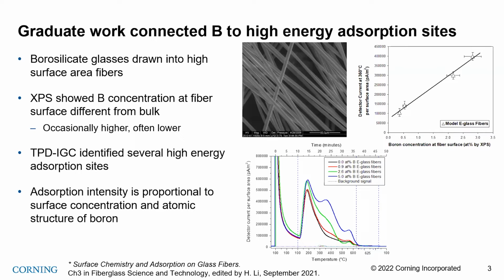So in my graduate work at Penn State, I focused on fiberglass, and this is kind of the epitome of high surface area materials, where the forming process, where you're drawing these into these 10 micron or so fibers, can alter the surface chemistry, either bringing some additional boron to the surface or actually, in some cases, depleting it. What we're able to show is that that level of boron and the structure that it takes at the near surface can introduce new adsorption sites.